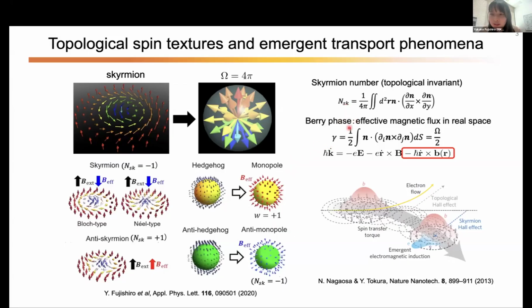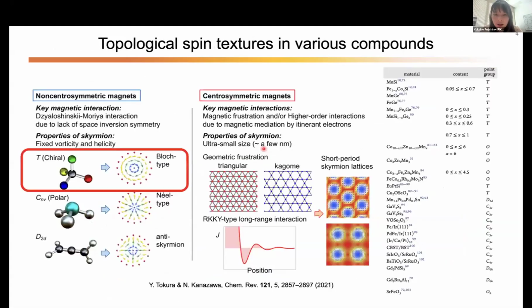In addition to this kind of classification, the transport measurement is a very important probe to detect the presence of these spin textures. This is because the finite skyrmion number of this spin texture actually affects the equation of motion in solids. When the electrons in solids are strongly coupled to the underlying topological spin texture, they acquire a Berry phase, which causes an additional Hall effect called topological Hall effect. So we typically use a Hall effect measurement to detect these spin textures.